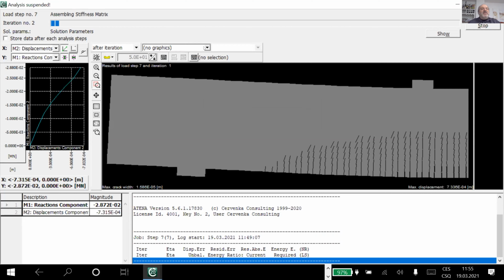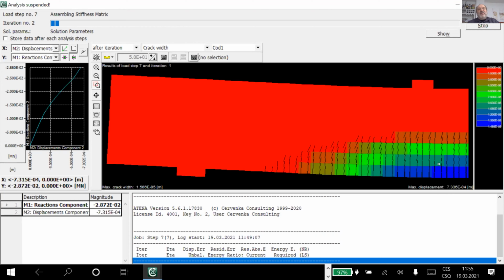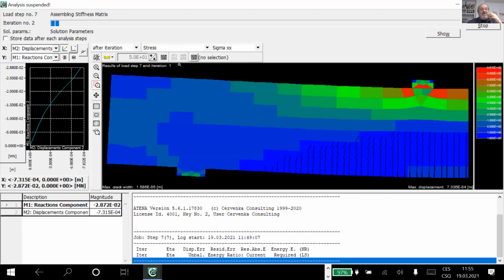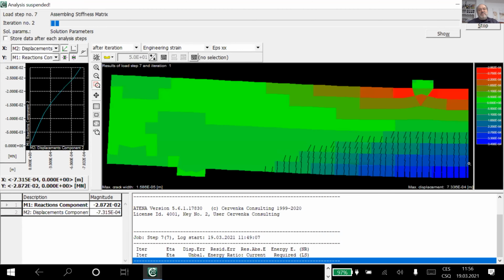And in addition, we can activate some graphical colored interpretation of results. The most interesting typically is exactly this crack width. So we can see that the main cracks are here, which is this maximum width, and then here are cracks which are much smaller. And eventually, what could be interesting would be the stress, but the stress, as you see, is concentrated typically around the supports and loading regions, and doesn't say too much. A better representative value is the strain, engineering strain. You can see the strain corresponds partially, because it's also going into the compressive region, but in tension it represents or corresponds to the crack width.